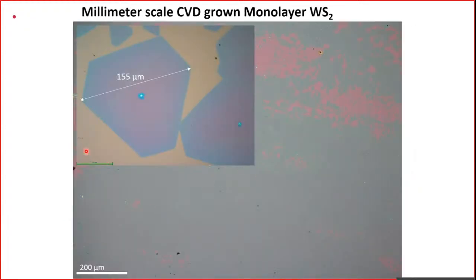So this is one example where we are able to grow at least millimeter scale CVD growth of WS2 monolayer. In the background you have an optical microscope image. Whatever you see here, if you zoom in, you will see flakes of 100 micron, 200 micron size. Unfortunately, it is still, I would say, not continuous. You can also see at the back the pinkish color substrate. That is silicon with 300 nanometers of thermal native oxide. So it is not continuous, but mostly flakes.